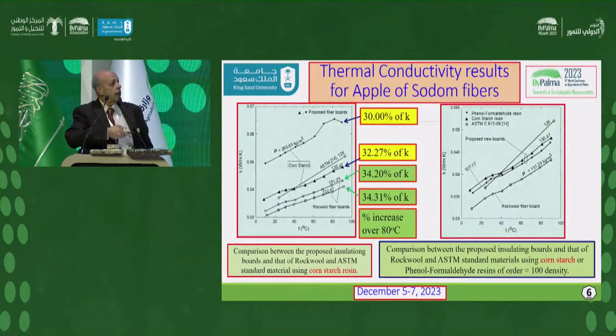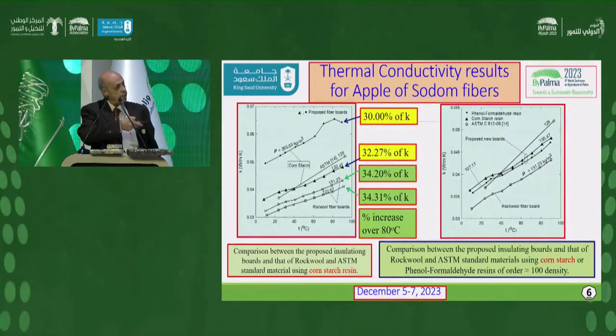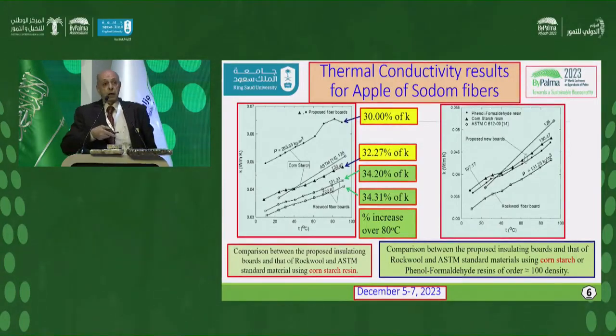This is the thermal conductivity, and as we see here, this is the thermal conductivity of the apple of sodom fiber. It's very close to the ASTM standard, so it's very good. Here are two samples. One is higher density, but this is low density. And these are another two samples which are very close to the ASTM standard. So it has a very good thermal conductivity coefficient. That's why I hybridized it with the palm tree surface fiber and with the pineapple palm tree leaves.